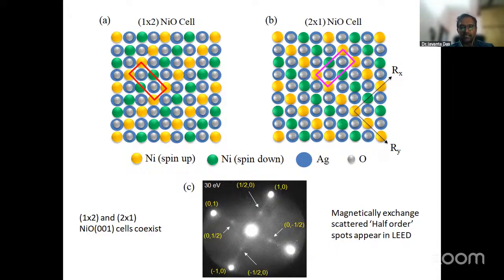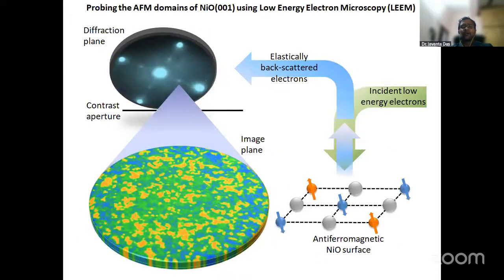And if we look at the in situ LEED, the low energy electron diffraction pattern, as I said, in reciprocal lattice you should expect the appearance of some extra lattice spots. In the diffraction, you will find these as the fractional order spots, the half-order spots. So in addition to the Coulomb scattered LEED spots, the 1-0 spots, you can find the additional magnetically exchange scattered half-order spots. We studied the intensity variation of these half-order spots, and from there we determined the Néel temperature and studied its variation. Moreover, utilizing these half-order spots, with the help of LEEM, the low energy electron microscopy, we have already probed the antiferromagnetic twin domains of nickel oxide, but that's a different story.